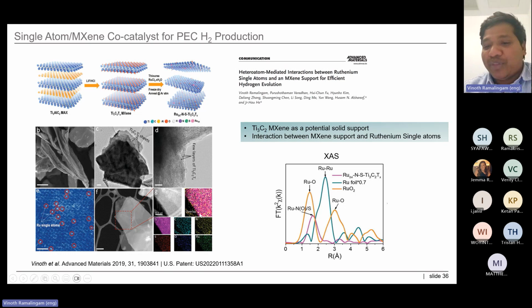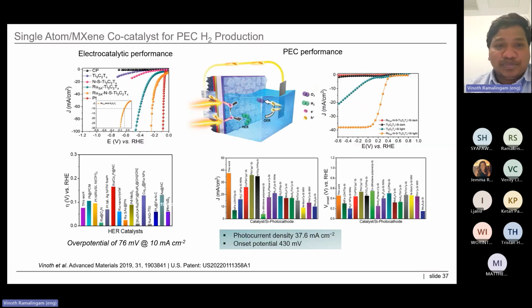1 nanometer. We have also done the synchrotron measurement, X-ray absorption measurement, to confirm that you have a ruthenium single atom metal, which clearly shows it's different when compared with Ru foil and Ru oxide. It's something different because we are trying to coordinate this ruthenium with nitrogen and sulfur. So we form the coordinated, interacted metal single atom with MXene support.